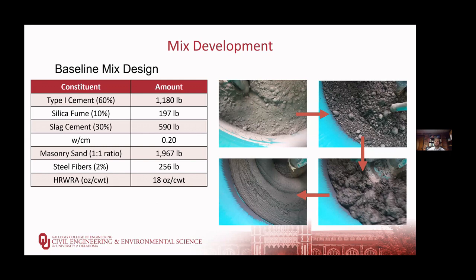And here on the right, you can see the mixing process for UHPC, where we go from all these powder materials. There's not very much water, so it takes a little while to mix, starts to ball up, and then eventually gives us this nice flowable cake batter-like material.